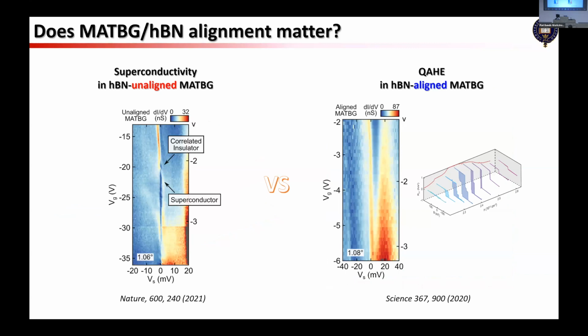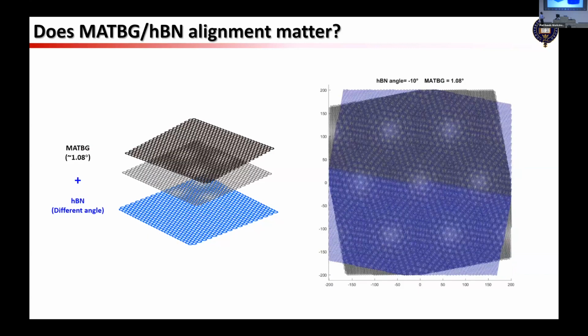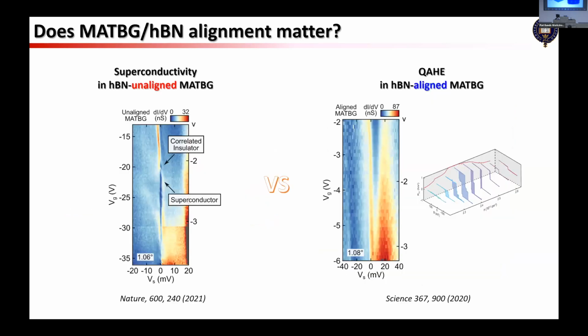But in the spectroscopy measurement, STM actually also found clear differences between the MATBG on HBN with different alignments. For example, superconductivity was only observed in the HBN unaligned MATBG. Unaligned means there's a very small angle, and in the previous slide, you can see that the modulation from the HBN is very high frequency. The period is much smaller than the MATBG intrinsic moire pattern.